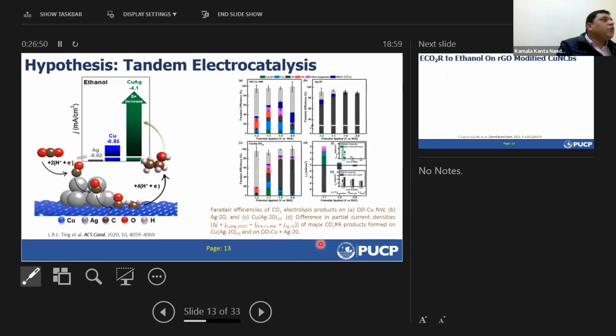So to enhance the product selectivity, we found a paper. They discussed the process of tandem electrocatalysis. Here they coupled a CO-forming catalyst with copper. The job of the CO-forming catalyst is to perform CO2 reduction and convert it to carbon monoxide, and the carbon monoxide gets spilled over to the copper surface and combines with CH2 to produce ethylene.